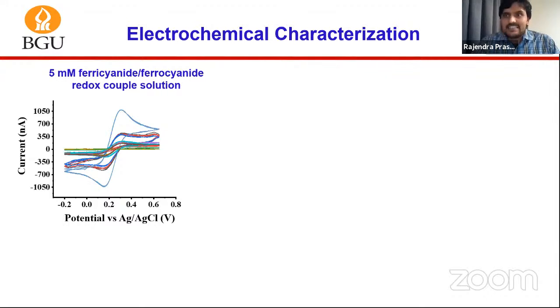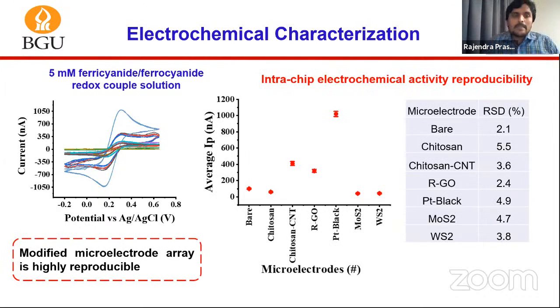So now comes the electrochemical characterization of this sensor array. This shows the cyclic voltammogram recorded in 5 millimolar ferricyanide solution. This is a redox probe, standard solution. And here you can see the different levels of the oxidation and reduction currents. That is because of the different electroactive surface areas from the differently modified microelectrodes, which is going to be good for our case that I will show you later. We also tested the intra-chip reproducibility of this sensor array, because for each modification we have 3 electrodes on the chip, and we found that the standard deviation is below 10%, which is good.